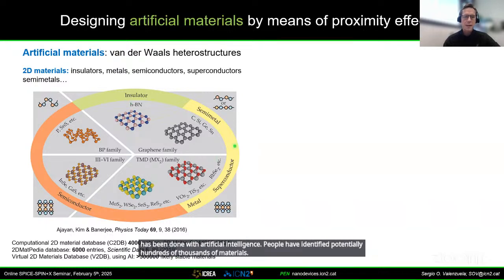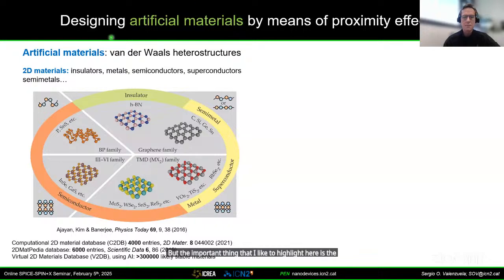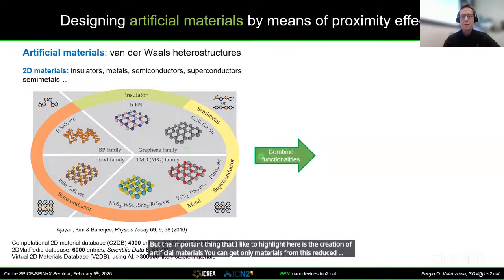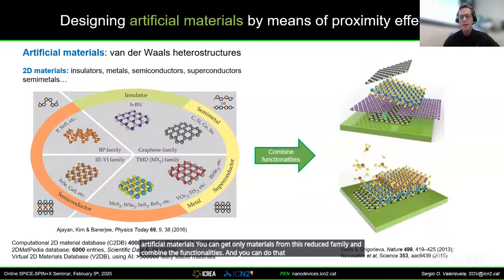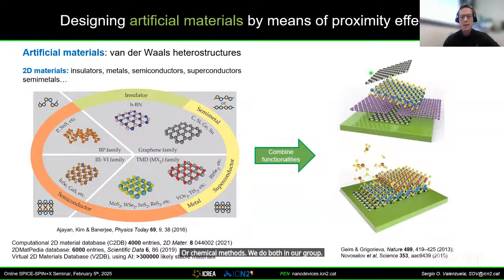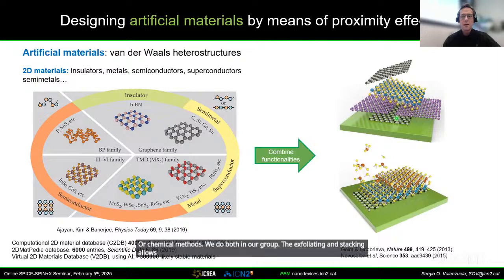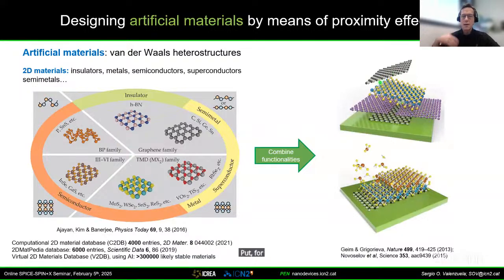But the important thing that I would like to highlight here is the creation of artificial materials. You can take materials from this reduced family and combine the functionalities. You can do that by exfoliating and stacking or by growing by physical or chemical methods. We do both in our group. Exfoliating and stacking allows you to make devices pretty fast with very high quality. This is something that you need to do eventually if you want to scale up the production of the systems. But the combination of the functionalities allows you to put, for example, a transition metal dichalcogenide, which is optically active, a semiconductor, with graphene, which has very high mobilities, with insulators and so on, and have a multifunctional artificial material.